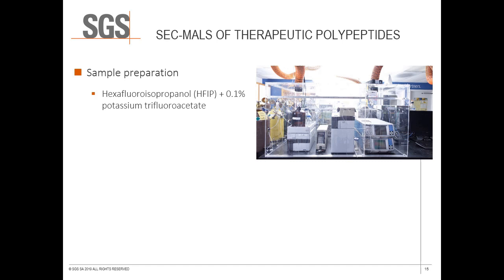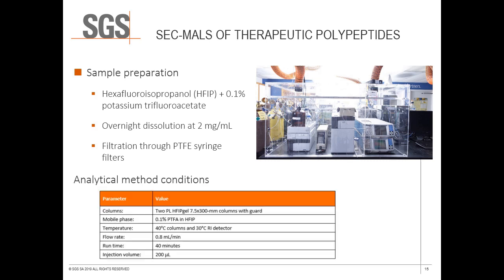This must be kept in mind when planning the sample preparation, as all samples prepared in HFIP must be filtered rather than centrifuged. Following overnight dissolution, the polypeptide was fully dissolved and was filtered through 0.45 micrometer pore size PTFE syringe filters. As these samples did not contain insoluble filler material or express any evidence of insoluble gels, filtration through smaller pore sizes or through filters with glass microfiber pre-filters was not necessary. Additionally, the expected molar mass of the polypeptide was in the tens of thousands, low enough to be unconcerned about the threat of shear degradation from gentle filtration. The filtered samples were injected on PL-HFIP gel full-size SEC columns under standard SEC method conditions for data collection.